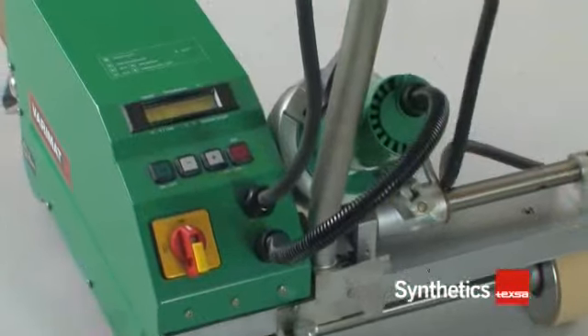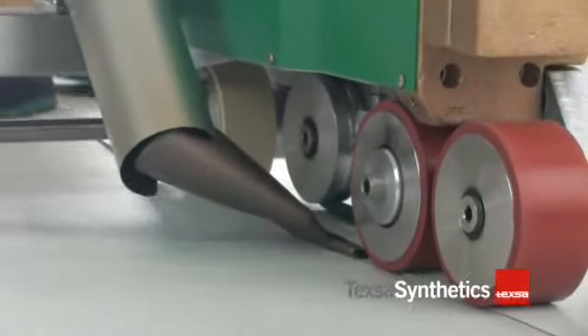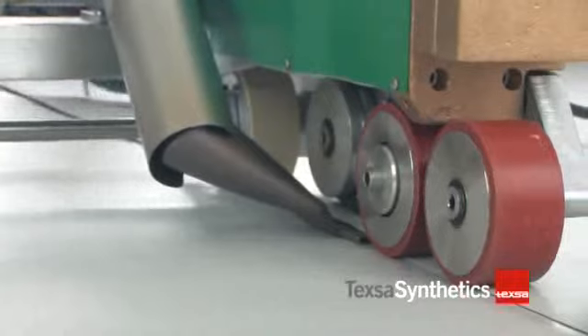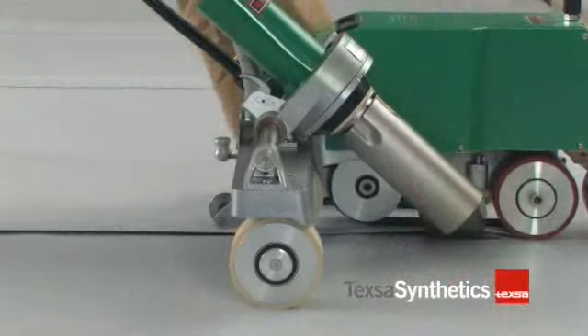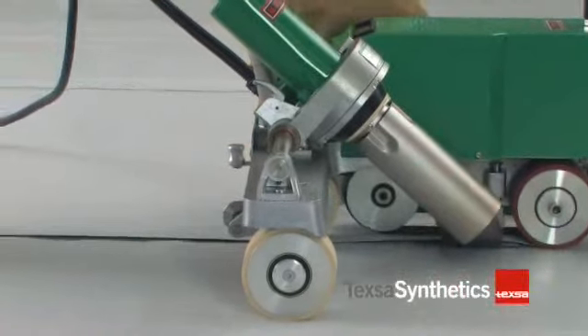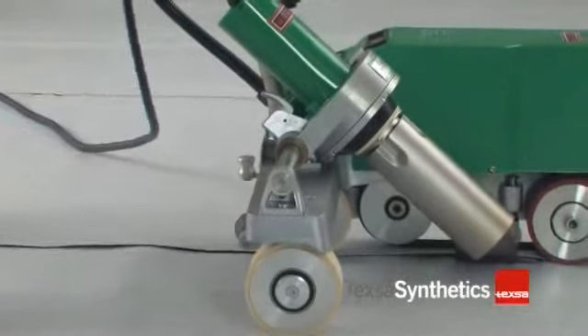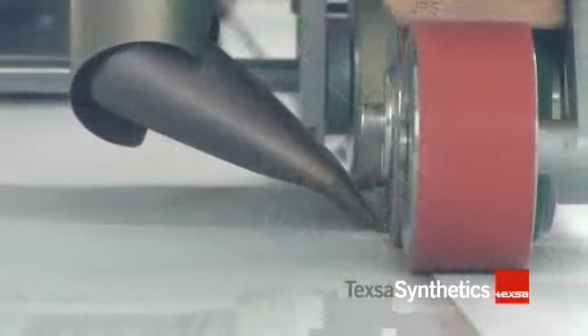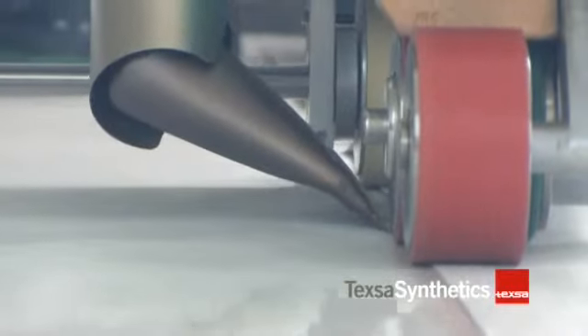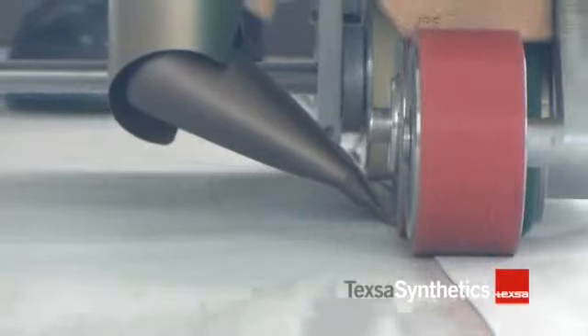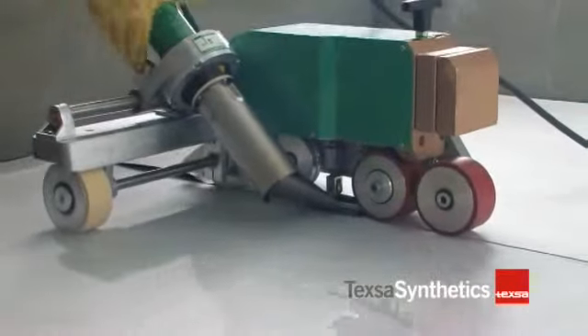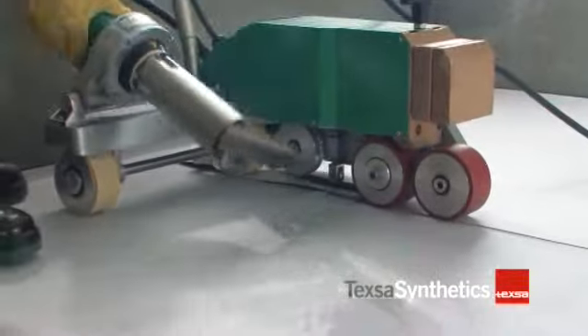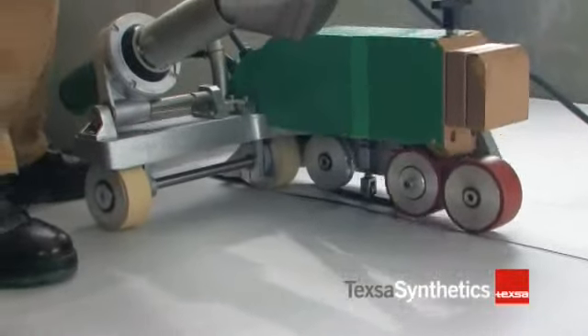Insert the nozzle under the overlap. The equipment starts operating when this movement is performed. Then weld normally, allowing the equipment to work at the programmed speed. With an air temperature of 25 degrees Celsius and using a 40mm nozzle, the recommended temperature is 560 degrees Celsius and a speed of 4.5 meters per minute.